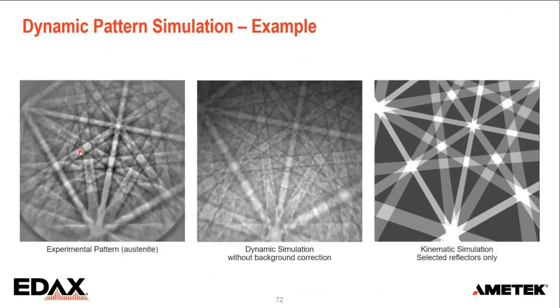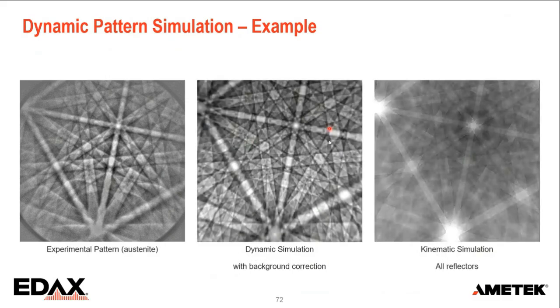Now, just to illustrate that, this is an experimental pattern, this austenite. This is the dynamic simulation, just looking at the intensity coming out. And this would be a kinematic simulation that we have also used in the past. You can recognize the bands, but of course, this doesn't look very realistic. When we then apply a background here, we get a lot of detail that we can compare with the experimental pattern. And on the kinematic side, we can add more reflectors. It gets a little bit better, but still not good enough.